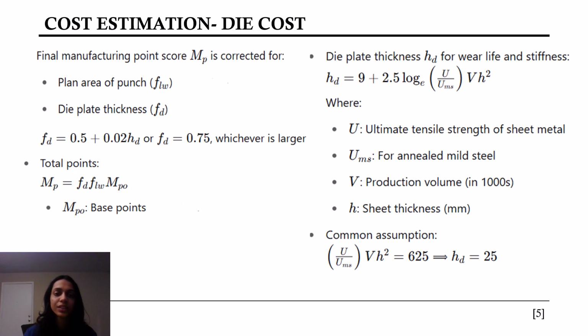So as the production volume or material strength increases, or when the sheet is thicker, the die needs to be stiffer and more wear resistant. Hence HD increases and so does the cost. A commonly used assumption is U over UMS times volume times H squared, which gives us HD of about 25 mm. This simplifies the analysis for average conditions.